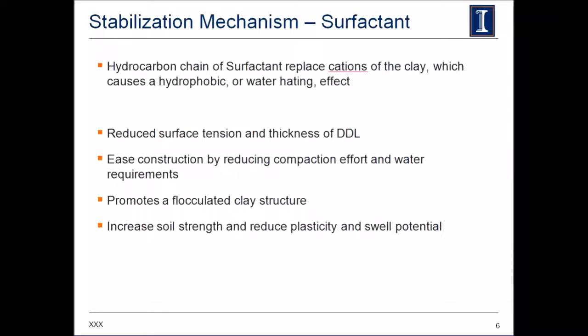Surfactants are generally organic and contain a hydrocarbon chain, which when comes into contact with clay will replace the cation of the clay soil. This ion exchange results in a partial instantaneous hydrophobic or water-hating effect, which reduces the surface tension of water and the thickness of the diffused double layer by allowing water to flow and dry more freely and easily.